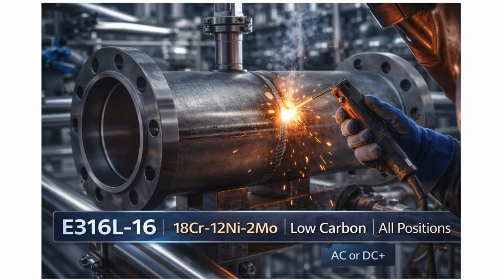Let's decode a full stainless steel example. E316L-16. Electrode, 316, alloy type, 18% chromium, 12% nickel, 2% molybdenum. Low carbon, max 0.04% C. -16, titania potassium coating, AC or DCEP, all positions. Use case: welding 316L stainless steel piping in a pharmaceutical or seawater service application. The molybdenum adds pitting resistance against chlorides, and the low carbon prevents sensitization.